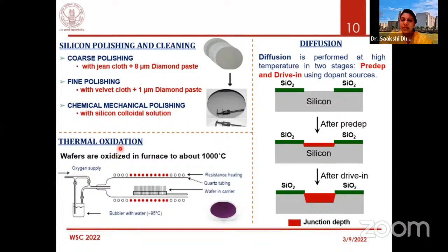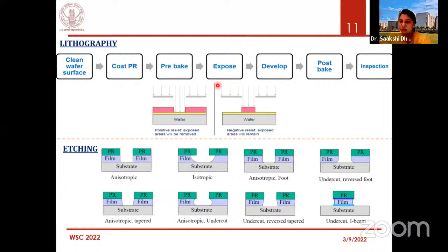Then comes diffusion, which is required when we are again performing P-type diffusion or N-type diffusion, right? In the beginning, we just see a small depth of the dopant layer, right? And when we remove that source and further keep it at high temperature, we see that this layer starts to seep in. And this is what really gives us the junction depth, right? Then comes our lithography, where we create structures, we create patterns on the silicon wafer, right? So how many we want, what kind of contact pad we want, right?